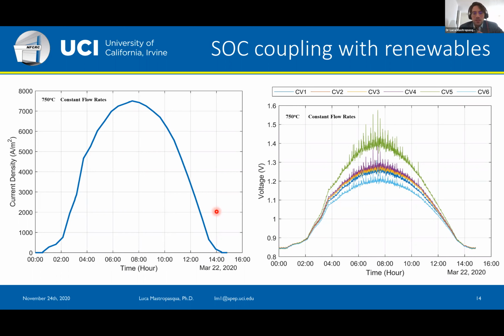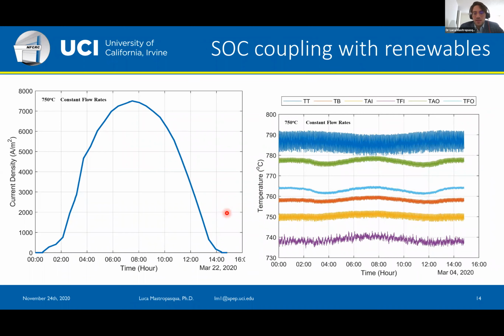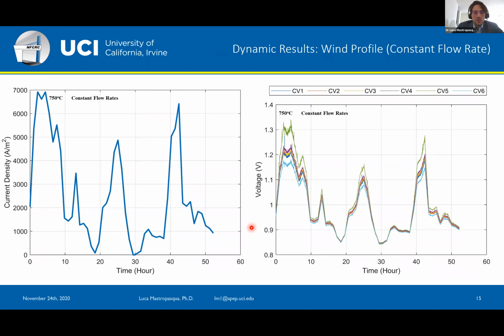This, of course, is a laboratory test stand. It doesn't have a complicated control system or a complicated balance of plant. But the main thing is that the temperatures of the stack are maintained constant. In this case, for us, it's simple because we have an electric furnace that maintains the temperature of the stack. But I think the main conclusion here is that for commercial systems, we must design control systems that are able to maintain the temperatures in the stack at constant or fairly constant levels in order for the system to operate dynamically and follow the dynamics typical of renewable energy systems.